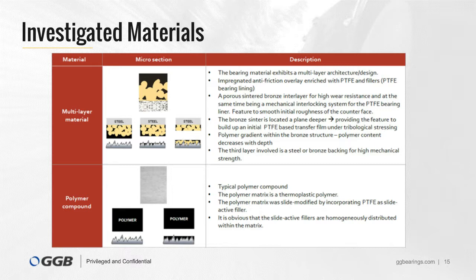It consists of a thermoplastic polymer matrix, slightly modified using PTFE particles. The microsection shows that the PTFE particles are homogeneously distributed within the thermoplastic matrix. We know that this material can also form a pretty stable transfer film on the counterface.